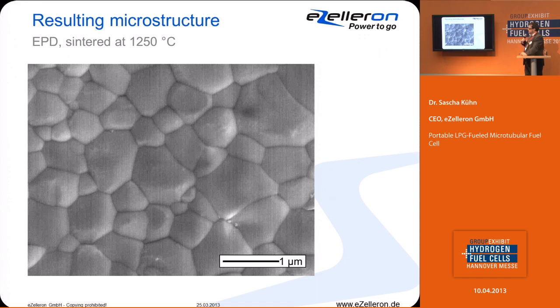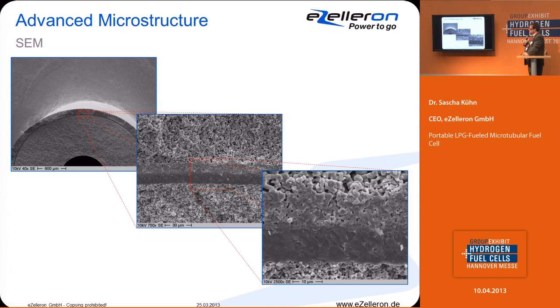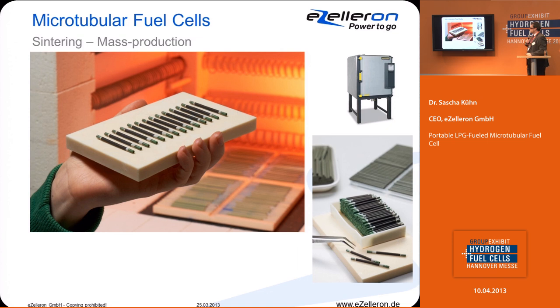The resulting microstructure is a microgranular microstructure, which means these layers have a very, very high thermoshock resistance and very good stability. Here you can see the whole microstructure again, starting with the tube on the left side. And in the last picture you can see that the layers are about 10 microns thick and almost free of any failures. We can mass manufacture these tubes.